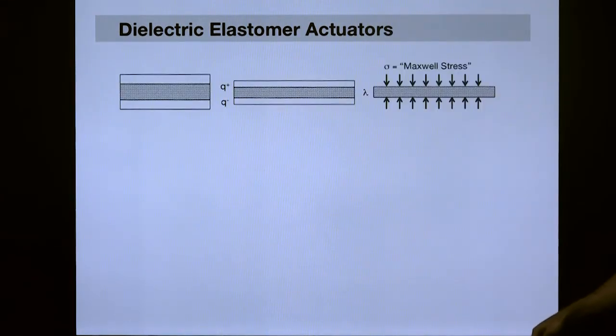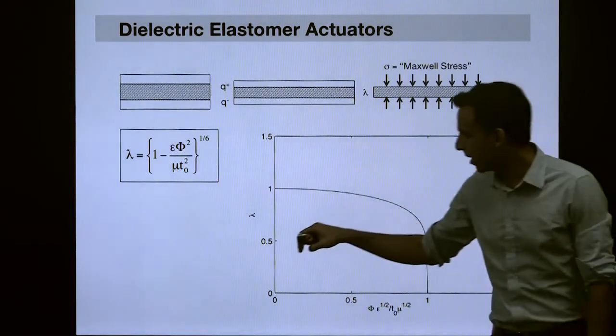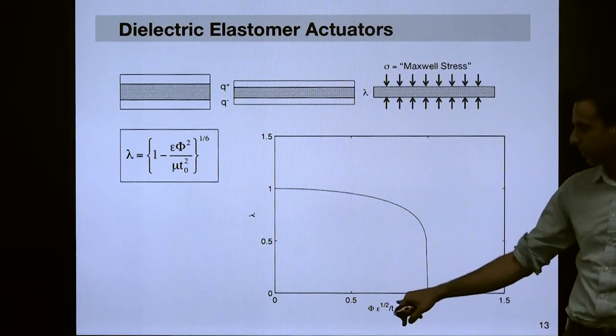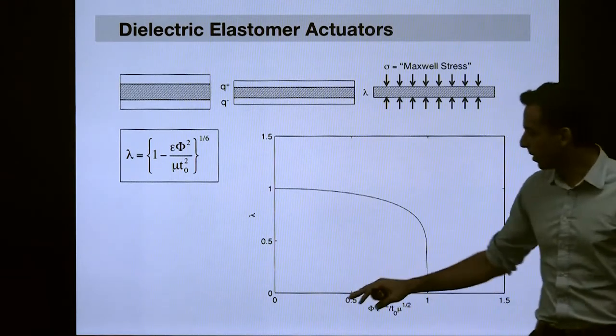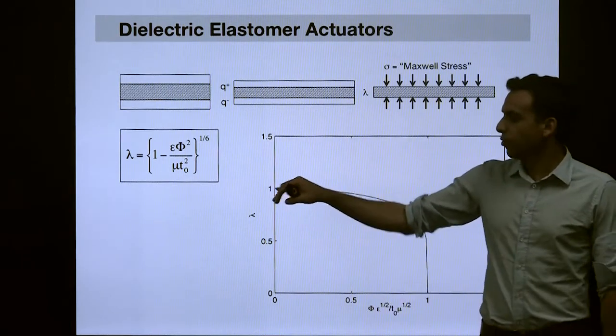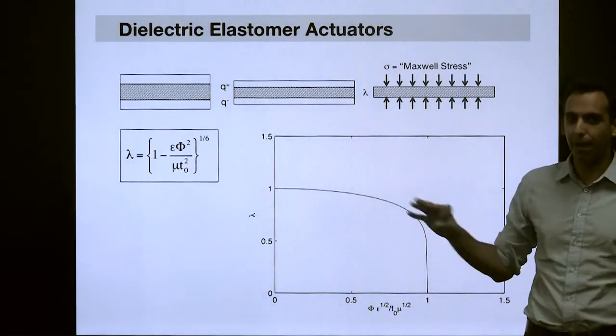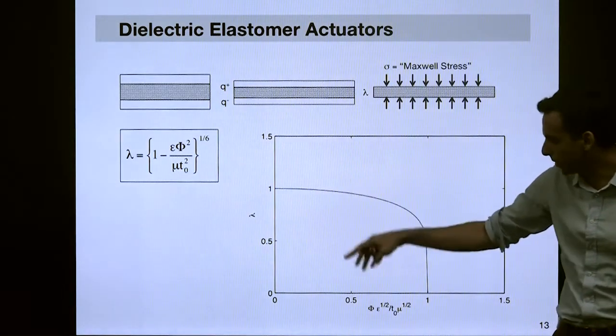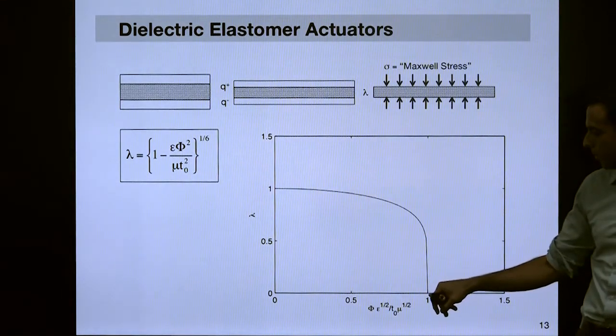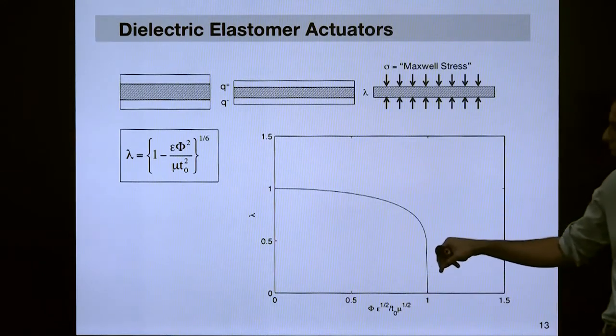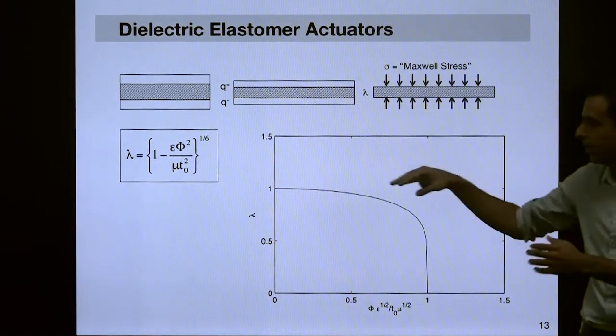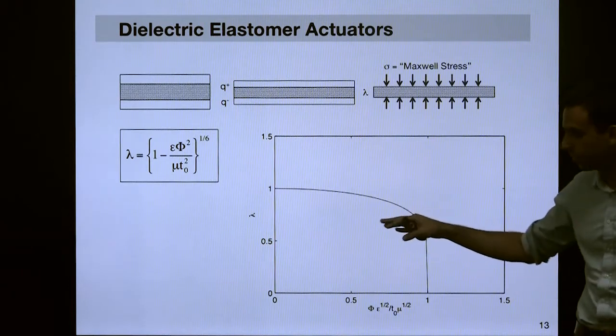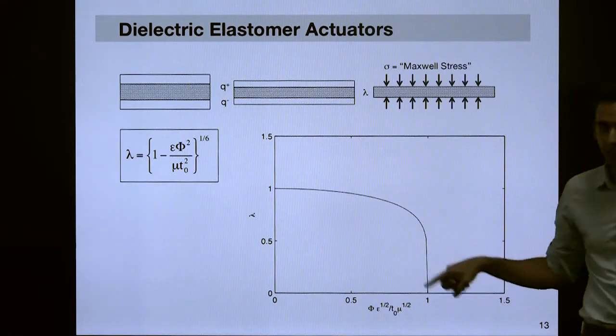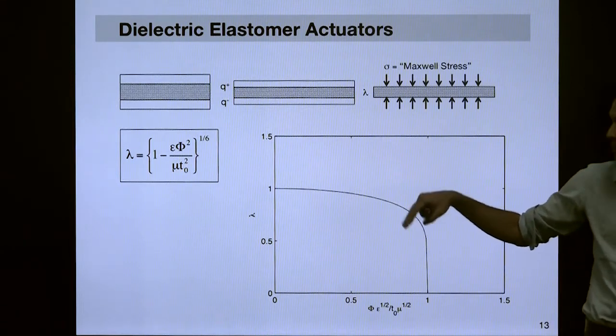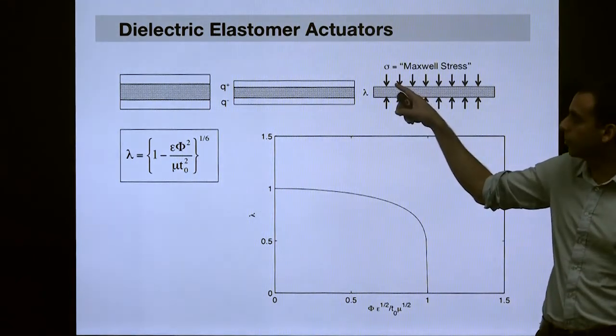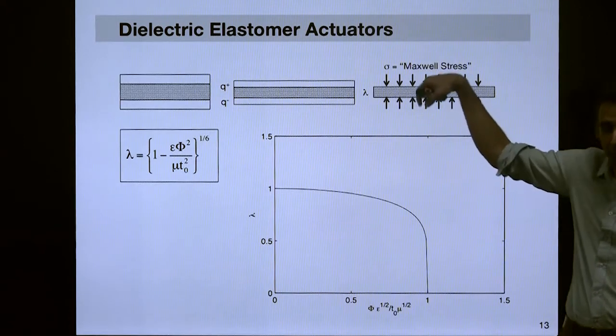And we can go ahead and plot that, and what we find is something somewhat unsettling. I've normalized voltage here with respect to parameters like thickness, the shear modulus of the solid, and its electric permittivity. Regardless of how you want to show this curve, the bottom line is that you apply all this voltage, kilovolts, like 1 kilovolt, 2 kilovolt, nothing happens. And then suddenly you apply, say, 3 kilovolts, and you see a little bit of change in thickness. And then you go to, say, 4 kilovolts, and then you get this instability. This electromechanical instability, where suddenly you go from basically no actuation, no response, to complete collapse and failure. This is catastrophic failure in the sense that you can't use your actuator after you've undergone this instability. In fact, before you even reach this instability, what typically happens is that the voltages will be so high that you'll get either electrical arcing around the insulator, or dielectric breakdown through the insulator.